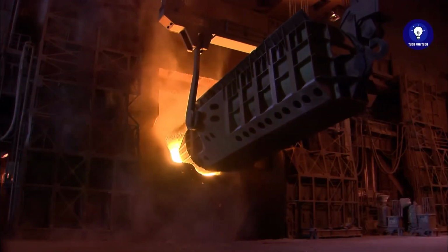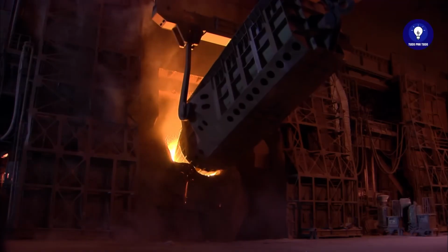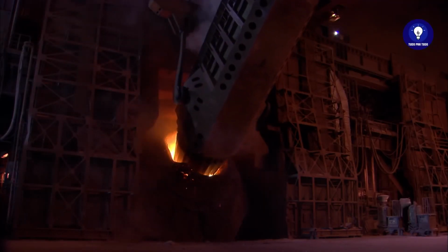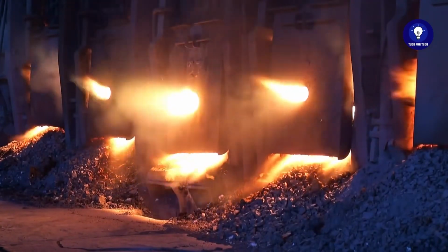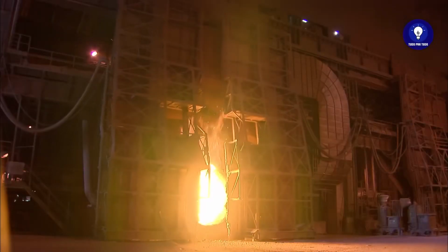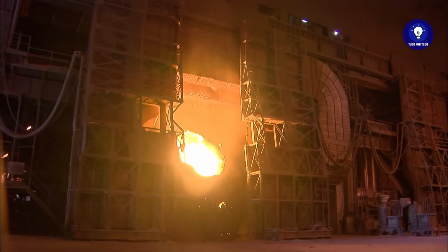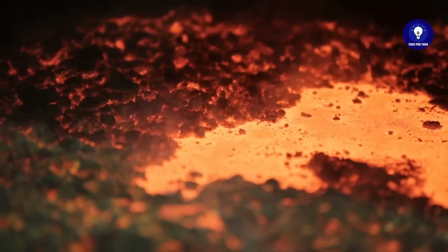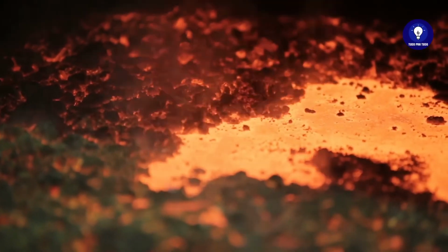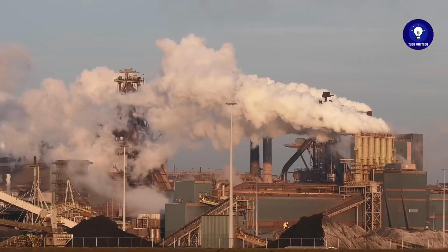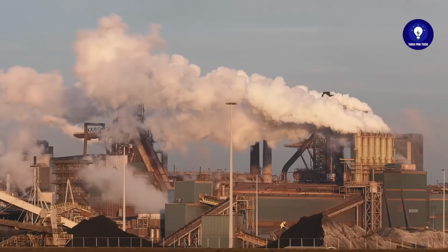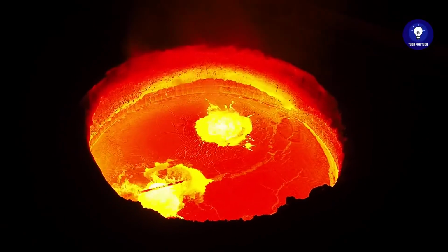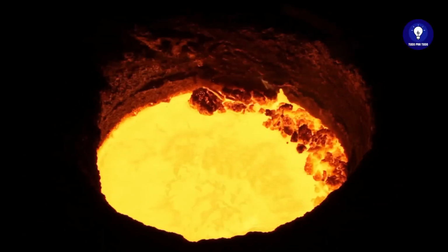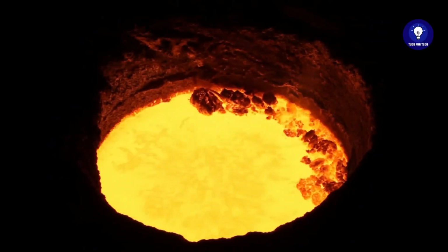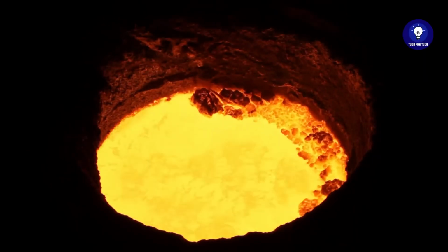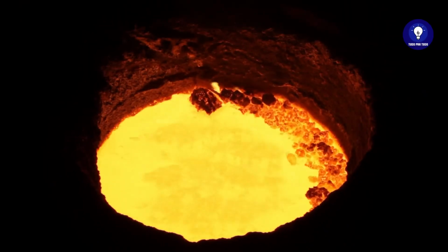From above, every few minutes, workers pour alternating layers of coke, iron ore pellets, and small pieces of limestone. At the base, blowers inject air that has been preheated in ceramic brick regenerators. Inside, temperatures easily exceed 1,500 degrees Celsius. The coke reacts with the oxygen in the air and forms carbon monoxide, which rises up the furnace column. Along the way, this gas steals the oxygen from the iron oxide, leaving behind liquid iron and carbon dioxide. The metal, now called pig iron, goes down and accumulates at the lowest part of the vessel, while the mixture of limestone and impurities turns into slag that floats on top of it.